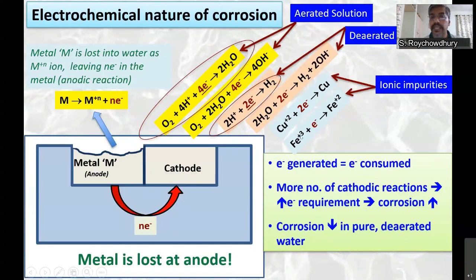Similarly, if you have ionic impurities, highly oxidizing ions like Cu+2 or Fe+3, they also take up electrons. So these are again additional cathodic reactions. The more cathodic reactions occur, the more demand there is for electrons, and all those electrons are sourced from only one reaction, the oxidation reaction.